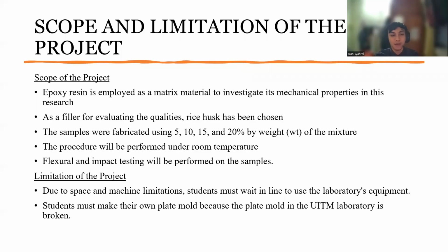Scope and limitation of the project. Scope of the project. Epoxy resin is employed as a matrix material to investigate its mechanical properties in this research. As a filler for evaluating the qualities, rice husk has been chosen. The samples were fabricated using 5, 10, 15, and 20% by weight of the mixture. The procedure will be performed at room temperature. Flexural and impact testing will be performed on the samples.